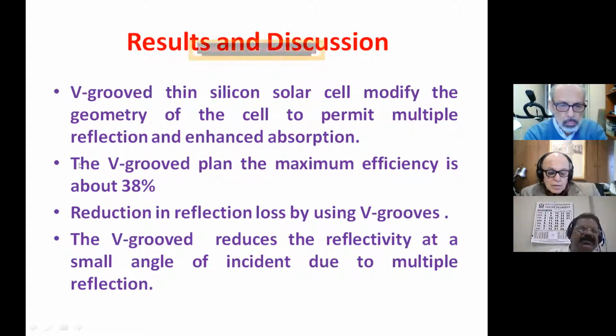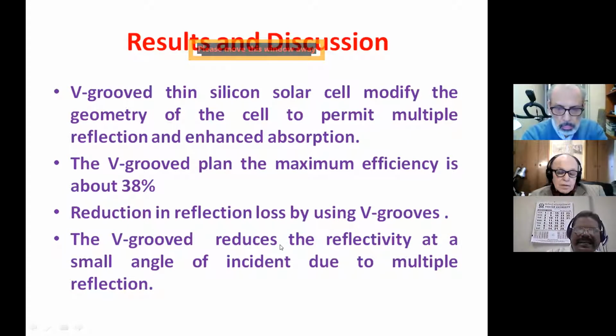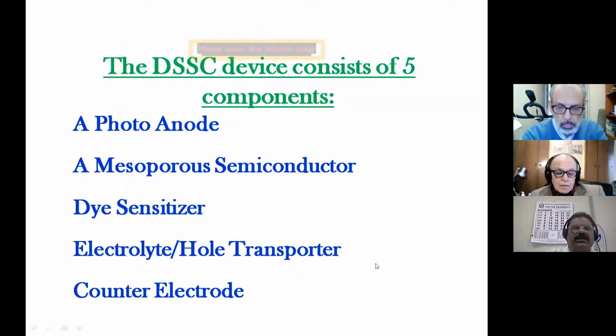So here the V groove structured shape makes use of the maximum efficiency of 38%. What will happen? The reduction in reflection loss by using the V grooves is achieved. Here the V groove reduces the reflectivity at a small angle of incidence due to multiple reflections within the cells. So next, for our comparison, we have taken dye-sensitized solar cells.